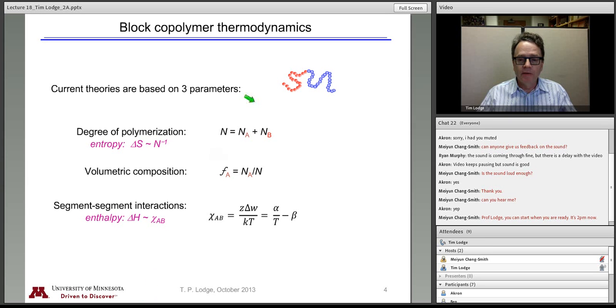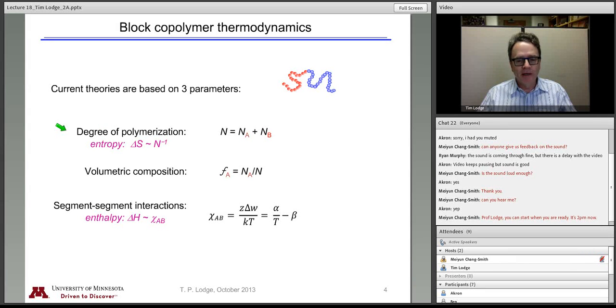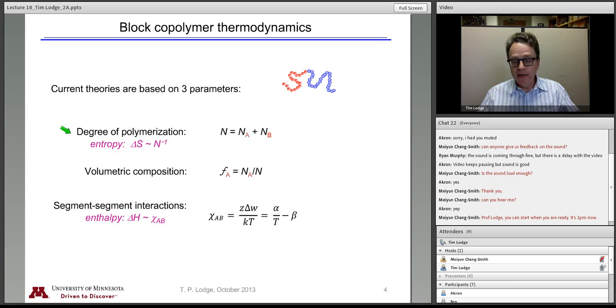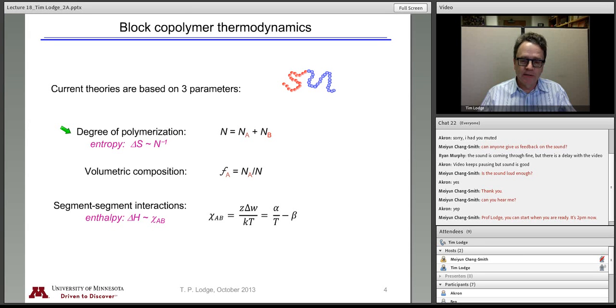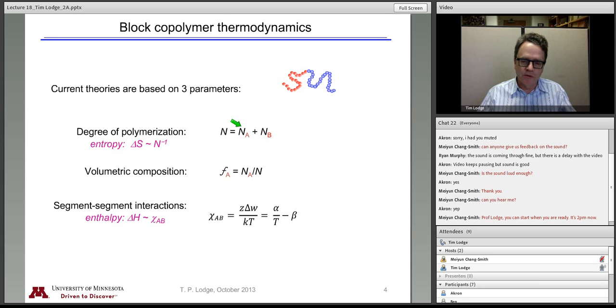The theoretical treatment of a diblock — an A polymer covalently linked to a polymer of monomer B — has thermodynamics dominated by three parameters. The first is the degree of polymerization N, which has contributions from both the A block and the B block. When calculating radii of gyration we might use the chemical degree of polymerization and statistical segment length, but for thermodynamics we want to define these separate N's on the basis of a common reference volume, which might be that of either of the monomers or some average of the two.